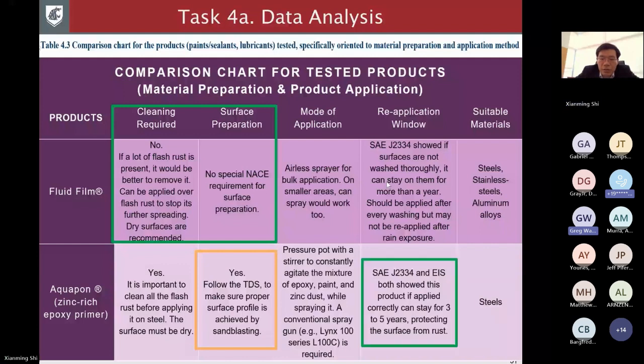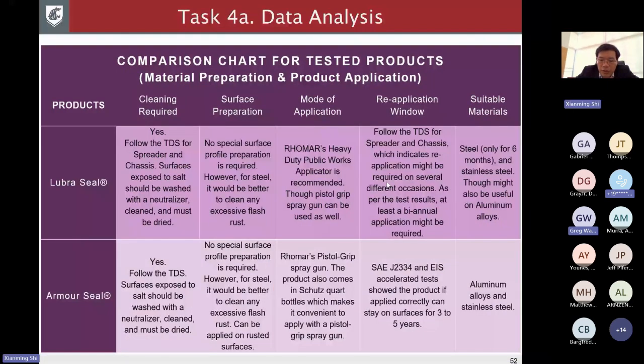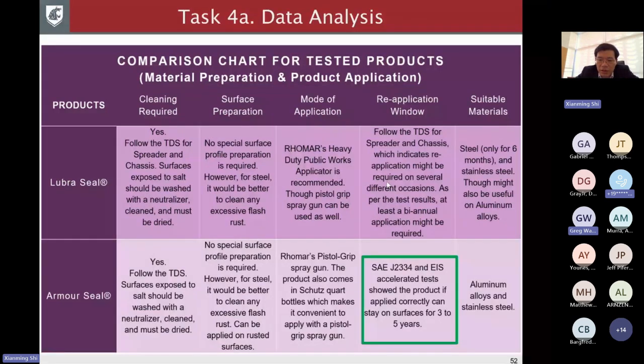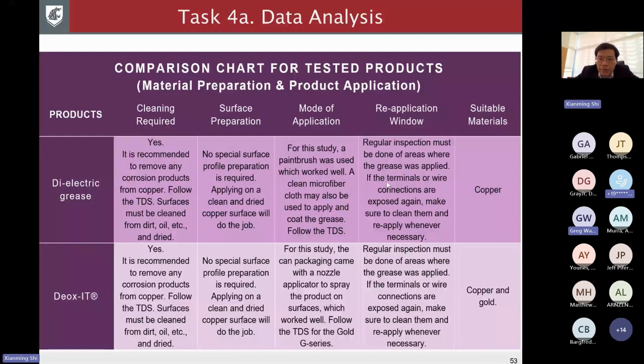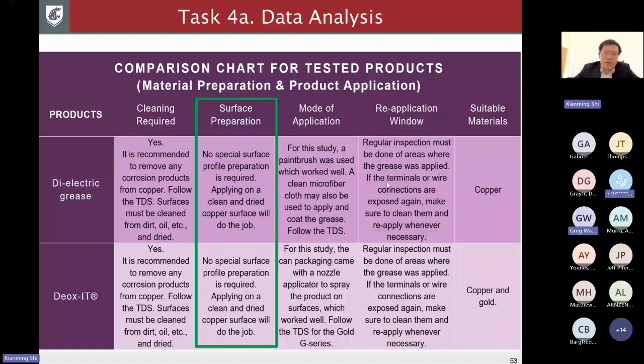Now, for the sealants, Lubra Seal versus Armour Seal, you can see here, Armour Seal worked better, especially for the surfaces tested, like aluminum alloys and stainless steel. It can last 3 to 5 years. In other words, they pass the cyclic salt spray test. But for Lubra Seal, the service life is only about 6 months on steel. Now, for the dielectric grease and other lubricant, again, the benefit is you don't need special surface preparation, but the downside is they both fail the 5-year test. So you need to reapply whenever necessary.